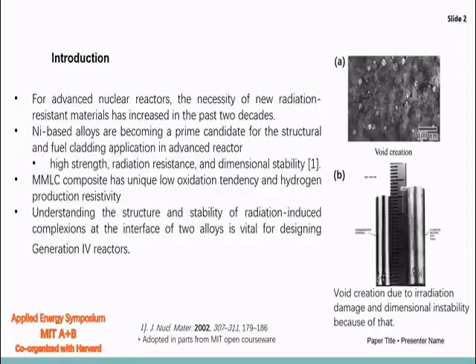In this study, we have investigated the nickel Inconel multimetallic layered composite because the multimetallic layered composite has a lower oxidation tendency and lower hydrogen production tendency. But the conventional zirconium alloys have a very high oxidation tendency and produce a vast amount of hydrogen, which leads to reactor meltdown accidents like Fukushima that happened a couple of years ago. The defects and the voids formed in the material can impair the mechanical strength and the dimensional stability. So it is very much important to study the material behavior under the reactor-like radiation environment for designing next generation nuclear reactor.